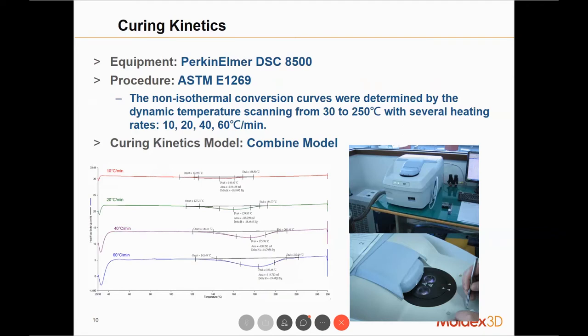Okay, so for the plastic injection stage, during the filling stage, the curing and viscosity are two of the most important properties that will influence our filling pattern. Because the higher the curing conversion rate is, the higher the viscosity will be. And with a higher viscosity, it'll be more difficult for filling, and later on it will influence our injection pressure, or if we're using a transfer molding process, then it will influence the transfer pressure. So curing and viscosity are two of the most important properties during the filling stage.